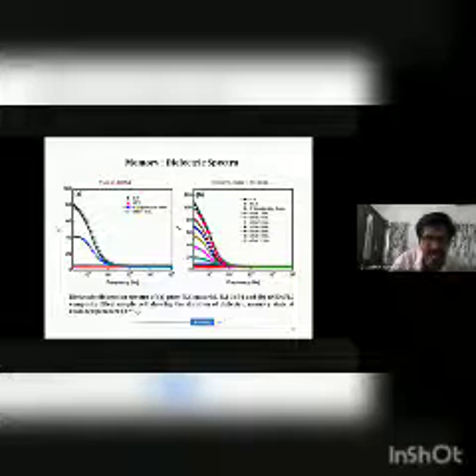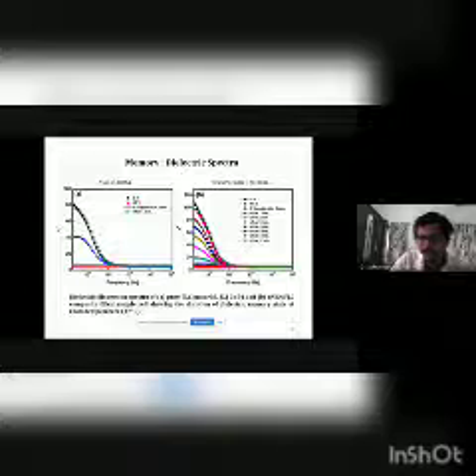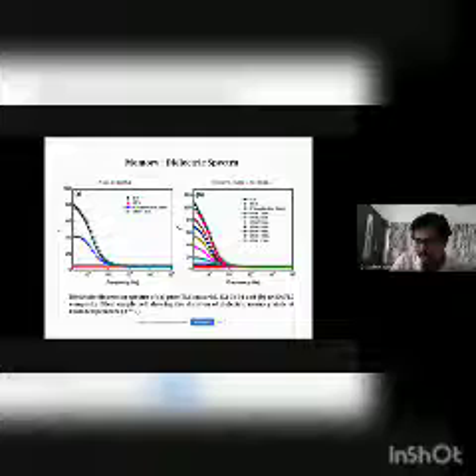When you are applying 15-volt DC as an external power, the complete molecules are being switched to one direction. So the permittivity has come down, and when you remove the bias for the pure one, almost after 1 minute it has returned to the previous state. So the memory duration is very short in the pure material, only up to 1 minute. But in your composite sample, you can see that the memory behavior lasts up to 10 minutes. You switched it, and it took up to 10 minutes to return to its previous state.